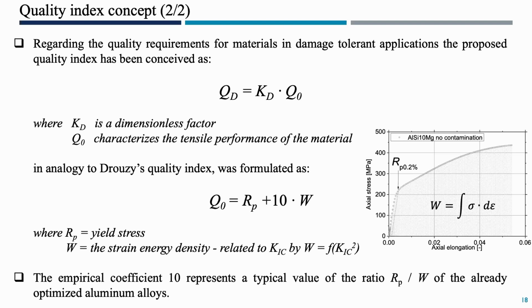Over the next decades, another quality index came up that merges yield strength and strain energy density. Strain energy density is, as you can see, the integral below the tensile curve, the energy needed for the material to break. And according to theory, the strain energy density is somewhat proportional to the square of the fracture toughness of the material.